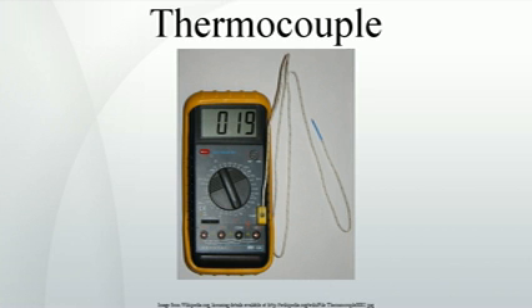A characteristic of thermocouples made with magnetic material is that they undergo a deviation in output when the material reaches its Curie point. This occurs for Type K thermocouples at around 350 °C. Type K thermocouples may be used up to 1260 °C in oxidizing or inert atmospheres without rapid aging. In marginally oxidizing atmospheres, such as carbon dioxide, between 800 °C and 1050 °C, the chromel wire rapidly corrodes and becomes magnetic in a phenomenon known as green rot. This induces a large and permanent degradation of the thermocouple, causing the thermocouple to read too low if the corroded area is exposed to thermal gradient.